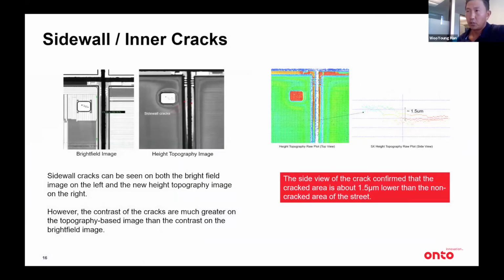And here is just another confirmation of a sidewall or inner crack. If you look at the two images on the left side, that's the suspected area with the inner crack. And you can see the bright field image is also showing some contrast, whereas the topography image in the middle is showing a lot higher contrast on the same defect, right? And the far right image is showing a cross section. It's showing that the crack, where the inner crack happened, is about 1.5 micron below the surface where it didn't happen. So this is just a confirmation that what we find as a high topography image is a real crack happening underneath the die surface.